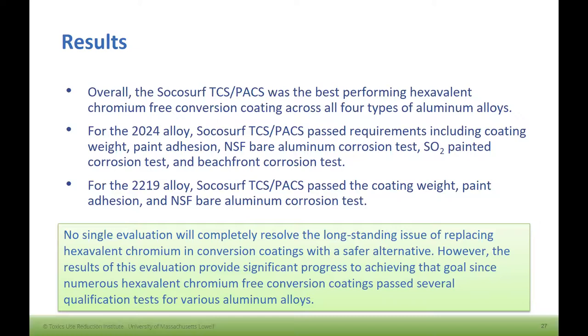And for the 2219, once again, Socosurf was the best. It passed several, but not as many tests were passed as the 2024 alloy, because again, the 2219 is much more challenging with the high copper content. So basically, in our paper, we wrote, no single evaluation will completely resolve the longstanding issue of replacing hex chrome in conversion coatings. However, the results of this evaluation provide significant progress to achieving that goal, since numerous hex chrome-free conversion coatings passed several of the qualification tests for various alloys.